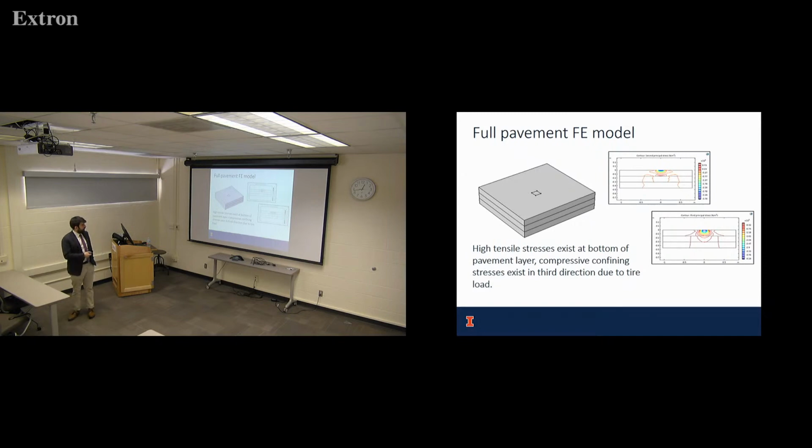And what we noted there is that the triaxiality is pretty low. There's not a high hydrostatic stress if you consider the asphalt as a continuum. Triaxiality factor overall is pretty low.